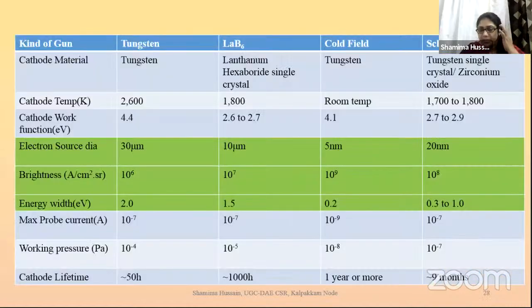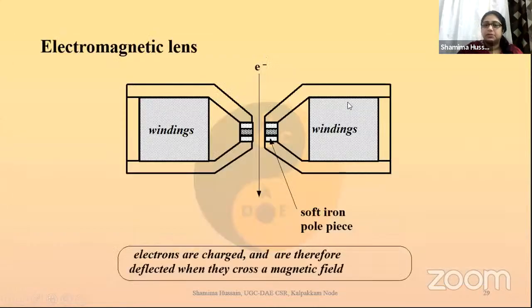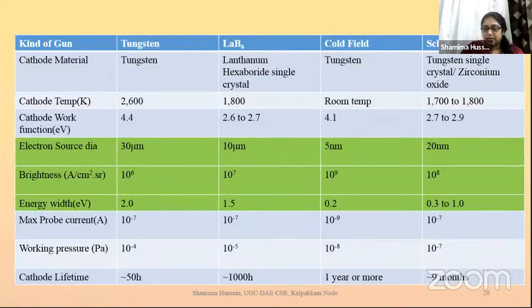I've just made a comparison in a table here, and all we see is that when I have tungsten, the temperature is something like this. With lanthanum hexaboride, it is about 1800, so we need a cooling element also there, sorry. And then we had this FEG which is working at room temperature. We don't need any other cooling for the gun separately. Schottky again we have to have. These are the drawbacks. Hence, this is what has emerged as the easiest one.